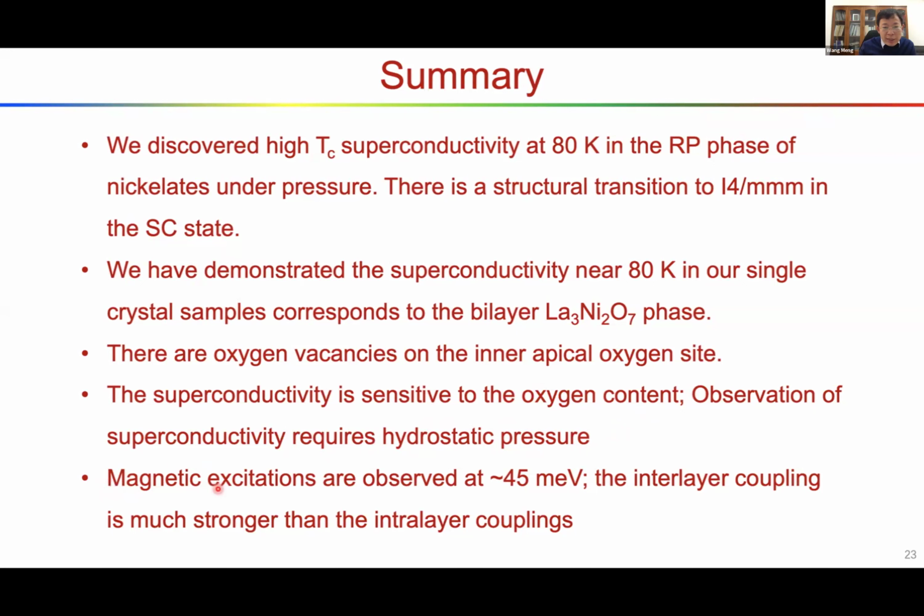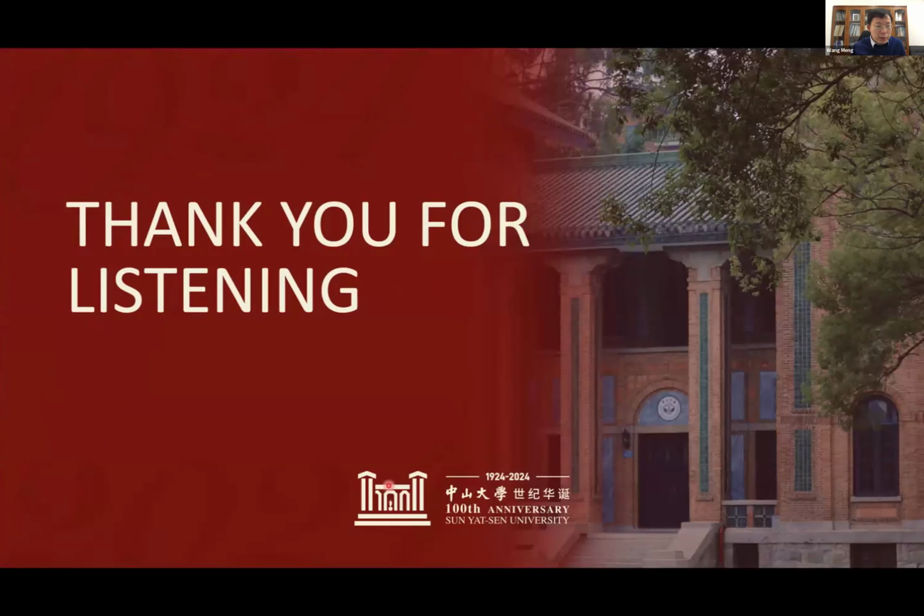We observe magnetic excitation at 45 milli-electron volts, and based on the observation, we can conclude the interlayer coupling is much stronger than the intralayer coupling. Okay, so that's all the information of my talk.